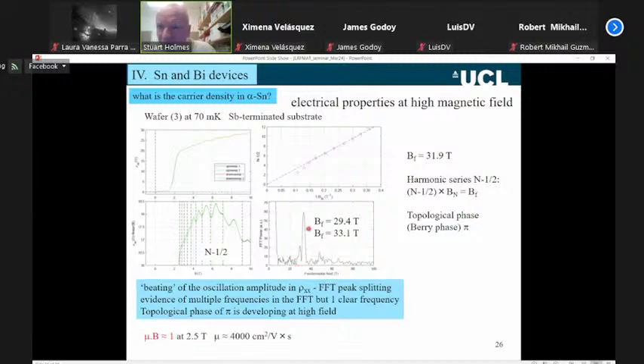Now, that's interesting. What we also found is that the minima in the Shubnikov-de Haas effect, the integer filling factors, don't correspond to minima in the magnetoresistance. These minima correspond to half integers. So the minima in resistance correspond to half integers. And we can kind of plot that out. They're a harmonic series. So we can plot the half integer on the y-axis as a function of 1 over magnetic field. That gives us this harmonic relationship.